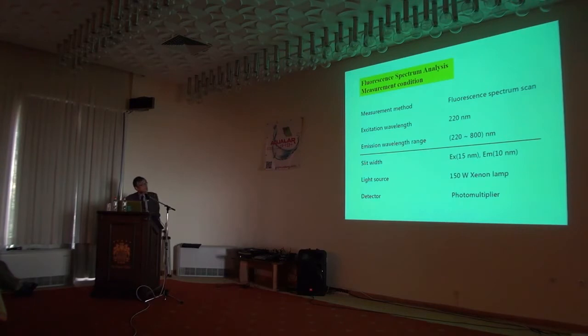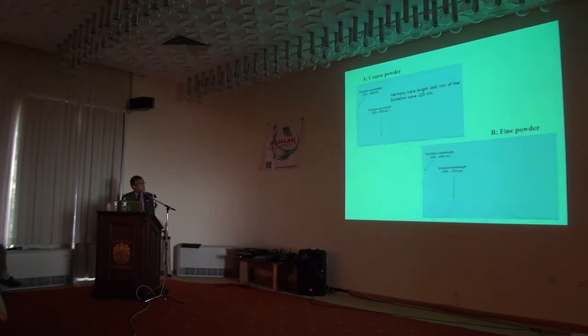And I tried to apply fluorescence spectrum analysis to observe if there are any fluorescent properties in the materials. An excitation wavelength of 220 nanometers was used for the excitation. And I found that an emission wavelength of around 370 nanometers was observed. This is the harmonic wavelength, so it's really induced by the excitation wavelength. So the meaningful peak is here.